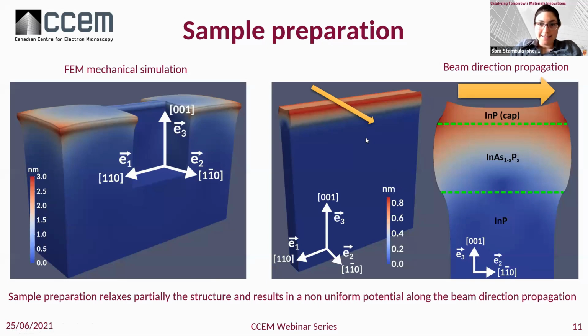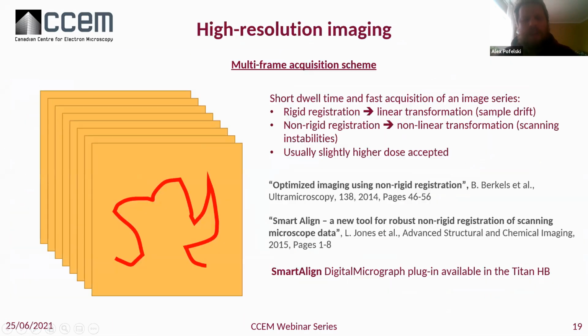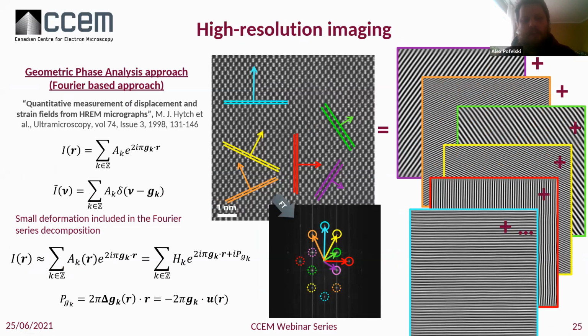So Rohit asked, is it advisable to do strain estimation on FFT/IFFT processed images? Yes, absolutely. This is what the GPA method is based on. My point here would be: do you look only at the FFT itself, because it is possible to see some aspects on the FFT already, or do you use the GPA approach, where you mask an area of the Fourier transform, then come back into real space and look at the phase variation? This is totally possible.